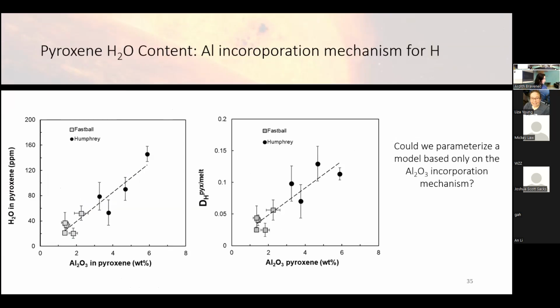So that looks fantastic. The next question is, how is water being incorporated in the samples? So for pyroxene, there's a known incorporation mechanism within the crystal chemistry that correlates with aluminum, and that aluminum creates a hydrous point defect, and that's how water gets into the crystal. So because of the aluminum incorporation mechanism, you expect to see a correlation with water contents in pyroxene and the aluminum content of the crystal. And sure enough, we do. And we also see the same correlation in the partition coefficient.